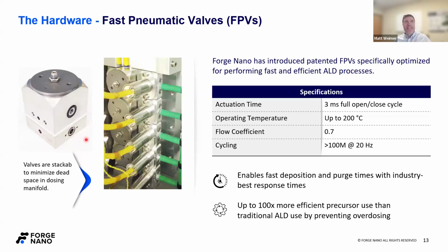Again, the less precursor you put in the chamber, the faster your ALD is going to go. And so we do what's called a face seal with these, where we stack them on top of each other to introduce precursor while minimizing that dead space. But really, the thing that sets these things apart is the actuation speed. We can do a full open close cycle in 3 milliseconds.